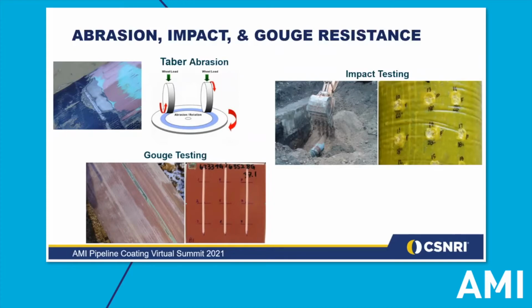In the top left photo, we can see abrasion damage over a girth weld down to bare steel. During pullback, coatings are subject to continual abrasion from soil, rock, and contact between the pipe surface and the borehole. At the bending point, a pipe will also be forced to conform by bearing against the side of a borehole. The elevated surface of a girth weld will certainly experience higher abrasive forces than the smooth mainline. A Taber abrasion test, as outlined in the diagram to the right of the abrasion picture, determines the amount of abrasion a material can endure. While lab tests show that composites are comparable to many field-applied coatings, many case studies show that the composite material prevents abrasion damage by taking the forces that otherwise would have attacked the coating.